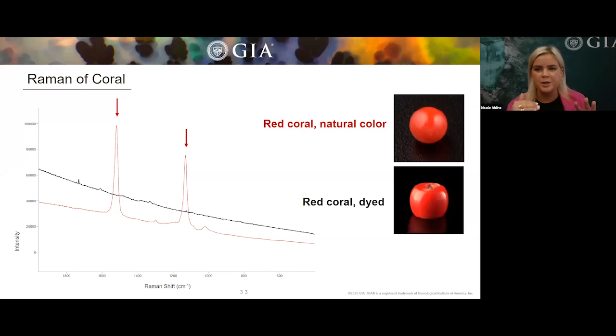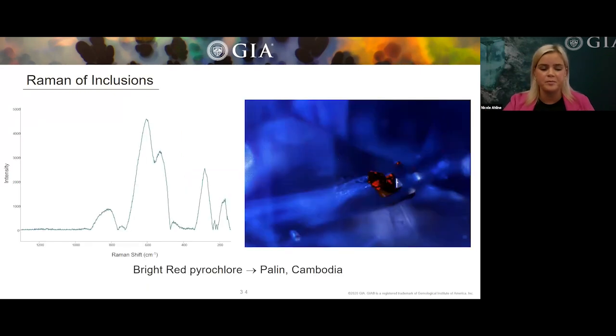So that red spectrum, or the black spectrum that's overlaid with it, those two peaks are absent. And so that was run against a red color piece of coral. And since those carotene peaks are absent, the gemologist is going to be leaning towards a dye call for this stone, because again, we're looking for those two peaks for a natural color.